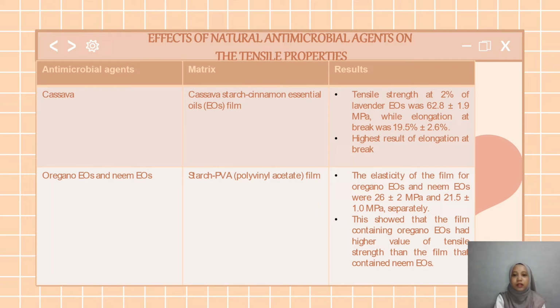The results are tensile strength at 2% of lavender essential oils was 62.8 plus minus 1.9 megapascal, while elongation at break was 19.5% plus minus 2.6%. Highest result of elongation at break. Second is oregano essential oils and neem essential oils. The matrix is starch polyvinyl acetate film.